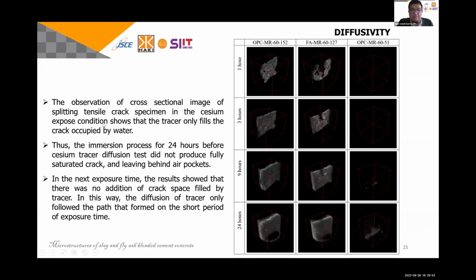Okay, this is thresholding. The observation of the cross-sectional image of the splitting tensile crack specimen exposed to cesium shows that the tracer only fills the crack occupied with water. Thus, the immersion process for 24 hours before the cesium tracer diffusion test, unfortunately, did not produce fully saturated cracks, leaving behind air pockets. In the next exposure test, the results showed that there is no additional crack space filled by the tracer. In this way, the diffusion tracers only follow the path that formed in the short period of exposure time.